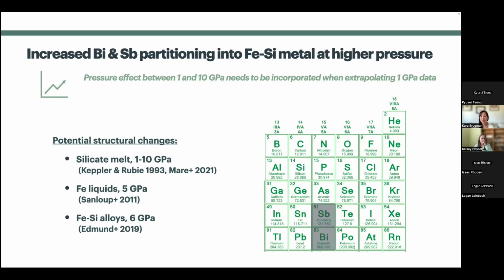Yeah. So one of the things that we tried to do in our experiments is that all of our experiments were conducted at the same temperature. And when we compare to the 1 GPa data, they are sometimes at slightly colder temperatures because you don't have to go as hot to melt at the lower pressures. So when you're comparing them, as I did on that plot, you have to correct for that, and there is a way to correct for the temperature.